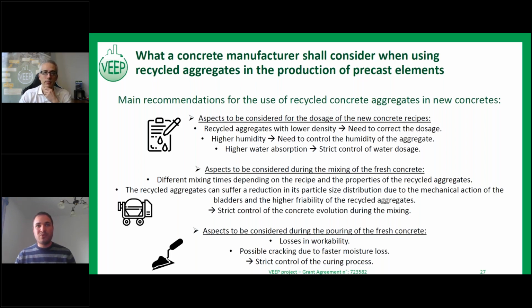So we have to consider some recommendations during the 3 steps of the concrete manufacturing. The first one is during the dosage of the new concrete. We have to keep in mind that we have lower density of the new aggregate, higher humidity, and higher water absorption. So we have to think in having a strict control of the water dosage and the constituent dosage of the new recycled concrete.